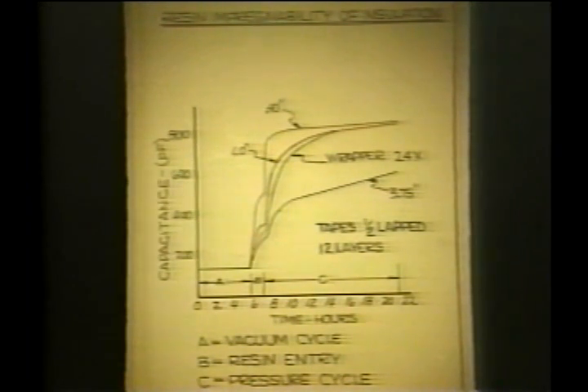The wider tapes impregnate at a slower rate, primarily because the tapes are applied tighter than the wrapper just for practical reasons. And the wrapper, even though it has fewer joints, because it is applied less tightly, it is more impregnable from the ends because of the wider spaces available. The point here is that it relates the impregnation rate to the number of edges in the tape. The narrowest tape having the most edges, and of course the wrapper having the fewest edges. And the point that was made in the paper was that even though the porous tape was used, most of the impregnation was occurring through the edges and along parallel to the surfaces of the tapes and not actually through the tape. And I think that's a concept that is important to remember.